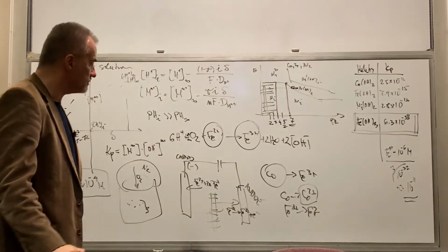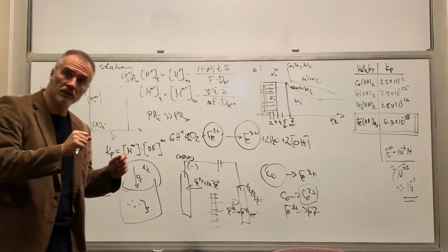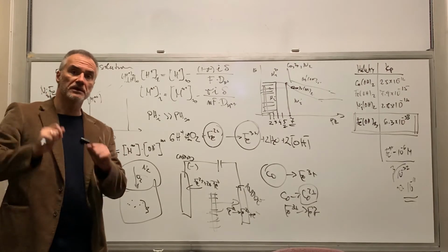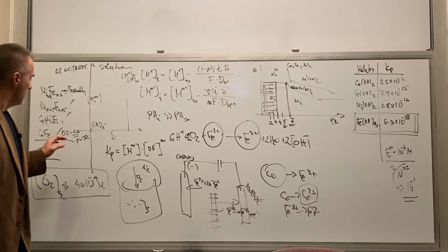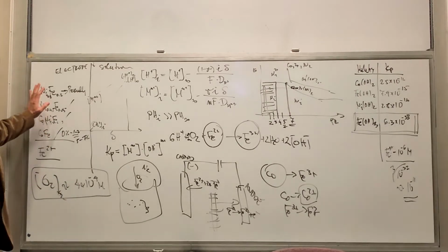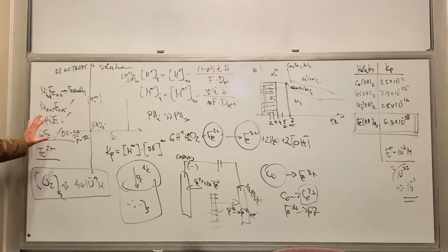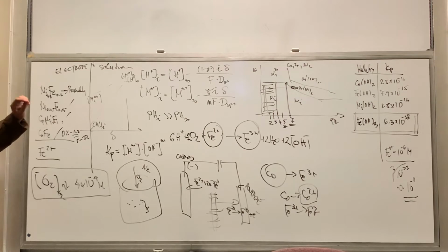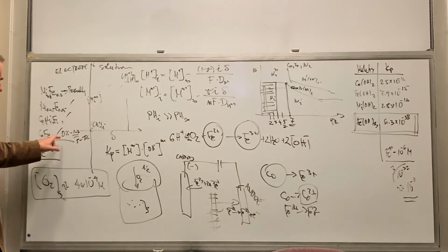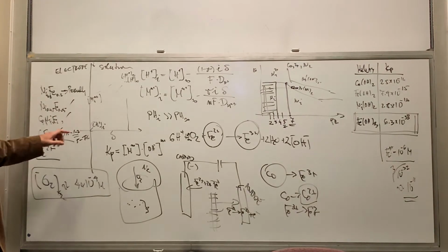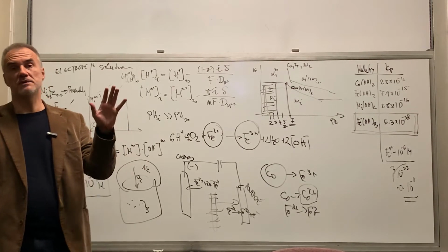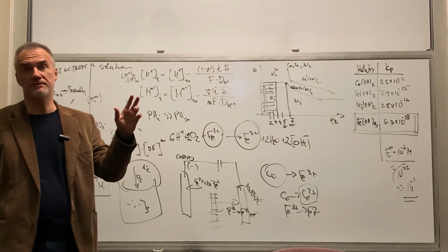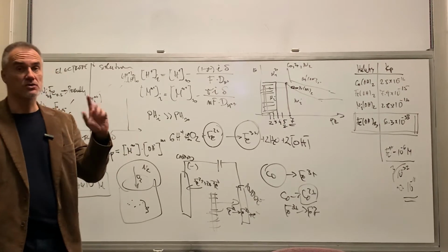Now, let me reverse the story, just tell you a little bit something else. For example, what David is doing for his PhD is he's trying synthesis of these magnetic alloys, and he's trying to keep them magnetically good, but he's also trying to put some controllable amount of oxide phase in order to keep resistivity high, because these magnetic alloys require high resistivity, high moment, and so on. Right?